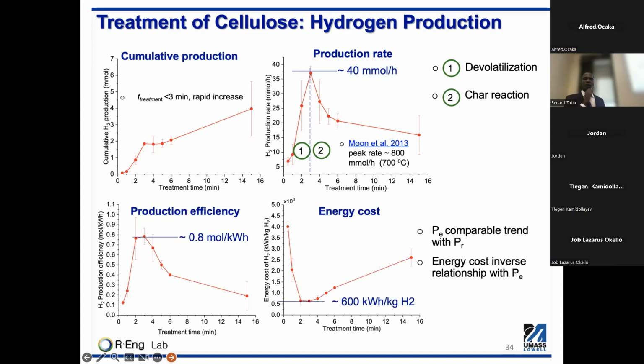And the energy cost of hydrogen production has more or less an inverse relationship with the hydrogen production efficiency. At a higher hydrogen production efficiency, it has a lower energy cost, and in this case, this is 600 kilowatt hours per kilogram of hydrogen.